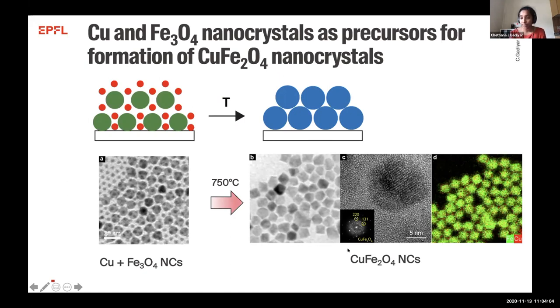The formation of this copper iron oxide was further characterized using high resolution TEM as well as elemental maps, which show that this is the copper iron oxide that we are forming. Once we knew that we were able to form these copper iron oxide nanocrystals, we wanted to understand the reaction mechanism that's taking place for the formation of this copper iron oxide.